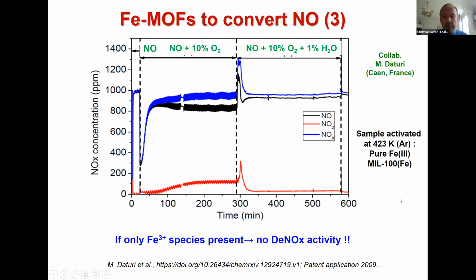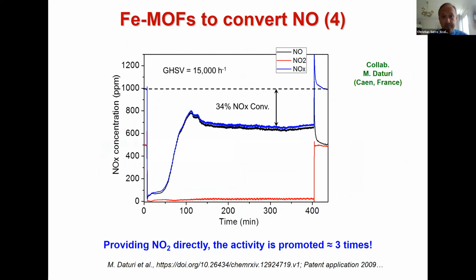What happens if you've got a pure iron 3 MOF? So you activate at 150 degrees Celsius only. Here you can see that you have a little bit of NO2, depending if you have or if you don't have water, but you do not have any evidence of nitrogen. So it means that there's no DeNOx activity if you have a pure iron 3 MOF material.